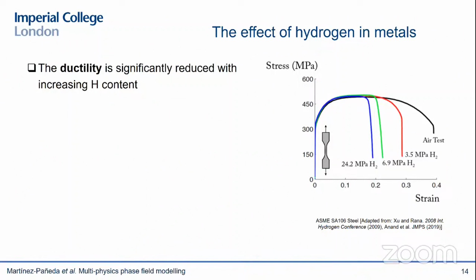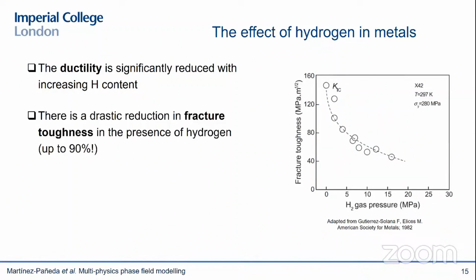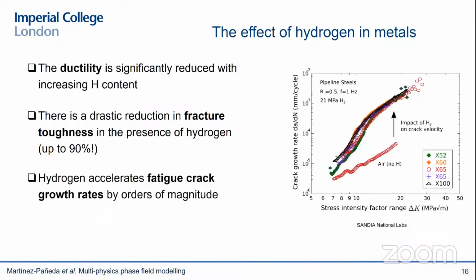failure strength. Another thing that we observed is a reduction in fracture toughness. You can see here that we go from a fracture toughness of 150 megapascal square meter to well below 40 megapascal square meter if I introduce hydrogen into my samples, for example, by exposing them to hydrogen gas. And this degradation in toughness also carries an acceleration of fatigue crack growth rates. So here you're showing fatigue crack growth rates without hydrogen and with hydrogen. And you can see this is a log scale. Hydrogen increases by orders of magnitude the crack speed under fatigue loading conditions.